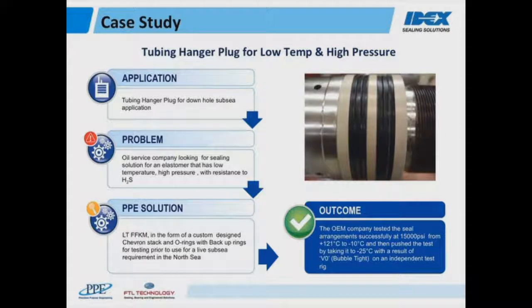Now the outcome was that the OEM company tested the seal arrangement successfully at 15,000 psi from a high temperature of 121 degrees C down to minus 10 degrees C, and then pushed the test by taking it even lower to minus 25 degrees C with a V0 or bubble tight seal, and verified on an independent test rig.